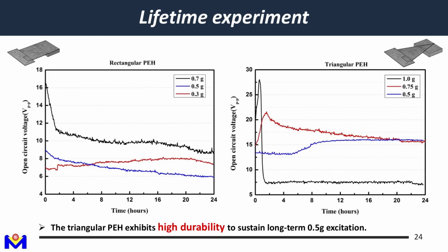And for the reliability lifetime experiment, we are now proud to say our device is quite reliable. Of course, the other reason, which I will mention later, is that we use a different substrate material. It's stainless steel instead of a silicon substrate. The stainless steel in the microfabrication process is more reliable because of better mechanical strength. So for the triangular transducer, you can see the blue trace and red trace at lower accelerations, 0.3 G, 0.5 G and 0.75 G. It lasts longer, and the output is constant compared to the rectangular.